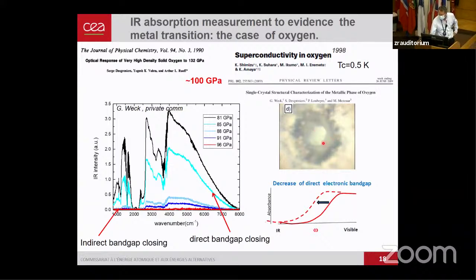Here is a single crystal of oxygen, which is like a metal, inside helium. And when you do the measurements with infrared in the same pressure range, exactly as we did for hydrogen, you see that you have a decrease of the intensity on the high wave numbers, and then on the low wave numbers you have a decrease. This is because there is an indirect gap closing, and then the direct gap is closing. I will come to that later. So we're confident that these infrared measurements are a signature of metallization.